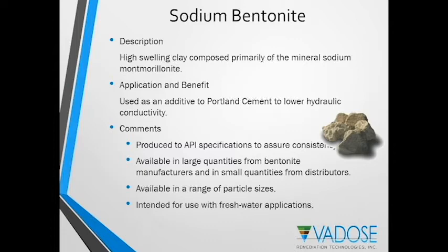Typically in an in situ stabilization application, you would use a powdered size grain and then mix it into a slurry. One thing also to note about bentonite is that it is intended for use in freshwater applications. It's important to know that sodium bentonite doesn't hydrate and turn into a slurry nearly as well in the presence of salt water as it would in fresh water.